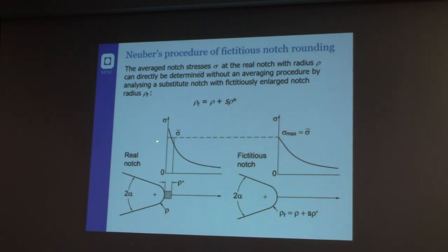They consider that the point value of the stress concentration factor is not very important for fatigue or fracture purposes, because, as we have seen in the diagram of Frost, if you consider the stress concentration factor you are too conservative in the design, because the notch is sharp and rho is very small. So what they tried to do is to average the stress over a material property length, rho star. They make the integral of the stress over this length, and the result is called sigma with a bar. But of course, if you have to make the integral every time, it takes a lot of time. So they proposed a kind of equivalent fictitious notch radius to solve the problem easily.